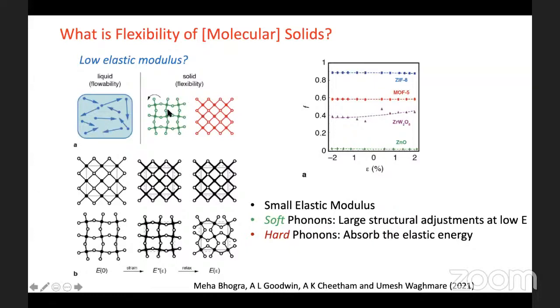So here, in the second row of this figure, if there is no internal degree of freedom in a crystal structure, the crystal cannot be flexible. Whereas if you have internal degrees of freedom, which preserve the symmetry of the lattice, you can have greater flexibility. On the right-hand side is a figure where we show different classes of crystals, starting from hard zinc oxide at the bottom. You will see the flexibility is very low. Then the negative thermal expansion material, zirconium tungstate, which is intermediate, then MOF5, which I described on the last slide, then ZIF8, which has the highest flexibility. So this measure is quite successful. I'm not going into details of it, but the insights it gives are very interesting.